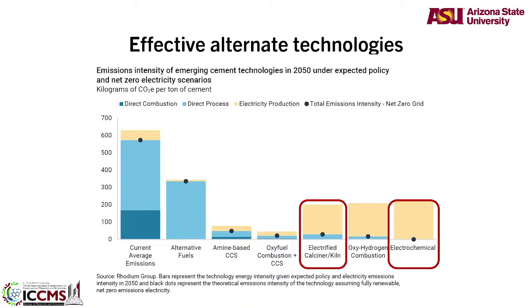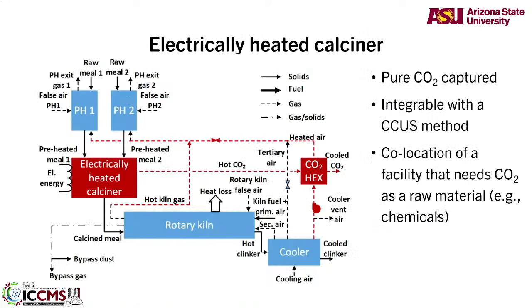If I calcine limestone alone, I get pure CO2, correct? Whereas in the current cement manufacturing, you are getting CO2 mixed with a lot of other gases that is very difficult to separate. And then if I do an electrochemical process, I have no process emissions. I'm not even breaking calcium carbonate into CO2 at all. And I'll show you quickly one slide on that. So here is one way of doing it. You have an electrically heated calciner, which basically means limestone is calcined by itself, not as a raw meal with everything, just limestone heated, which means you get pure CO2 that you can take off and sequester and do something else.